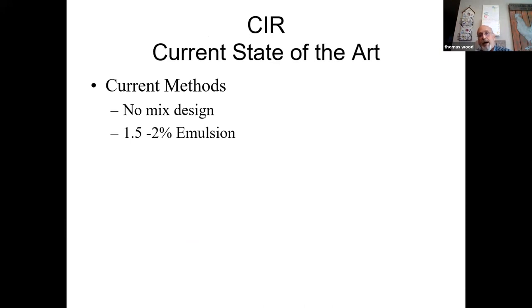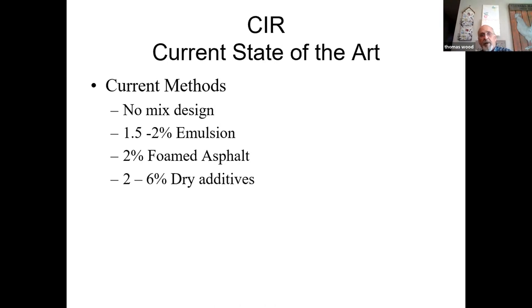Rule of thumb, without a mix design, is they're going to put 1.5 to 2% emulsion in. So if it's 60% asphalt in the emulsion, at 2% you're adding 1.2% asphalt. If you're doing foam, they usually foam it at 2% asphalt. So over here in emulsion, I'm at 1.2, and over here in the foam, I'm at 2. And I'm wondering about performance. I think the emulsion needs to be up close to 3, but that's just my opinion.